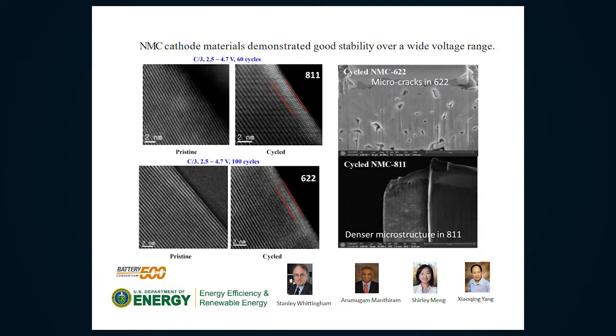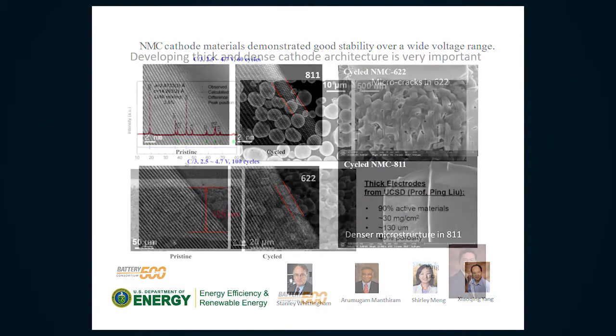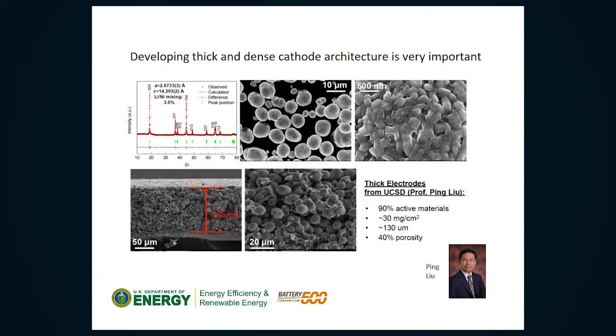And another thing is the surface stability. And you always generate a sort of a constructed surface layer on the NMC material. Fortunately, this one doesn't grow indefinitely. So you grow this surface layer, and then it stops. So that's the same for 811 and 622. So in that regard, the cathode material is pretty reasonable.